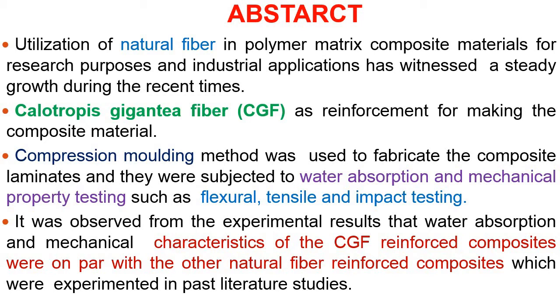In this work, we will take Calotropis gigantea fiber as reinforcement for making the composite material. When we are going for that composition of the composite material, we are using a compression molding method. Compression molding method was used to fabricate the composite laminates, and they were subjected to water absorption and mechanical property testing such as flexural, tensile and impact testing.